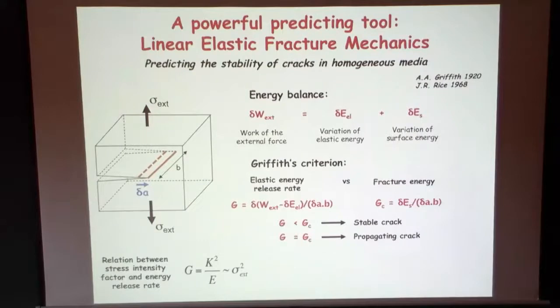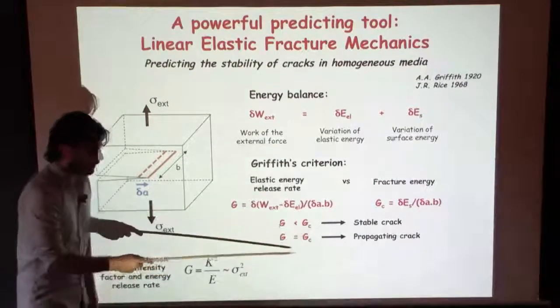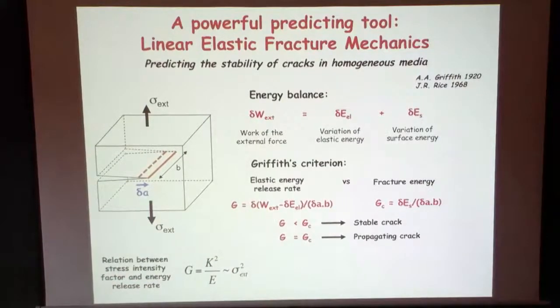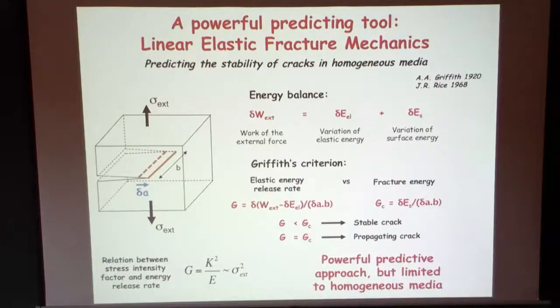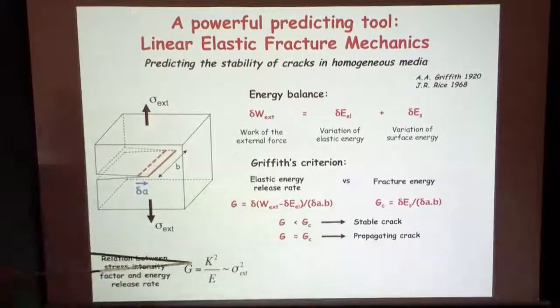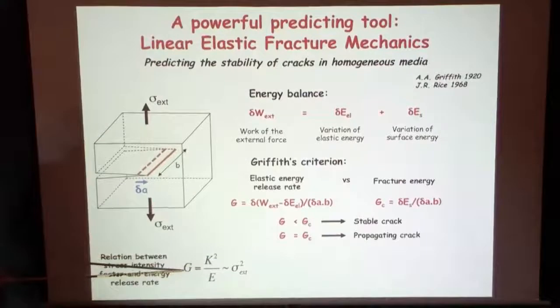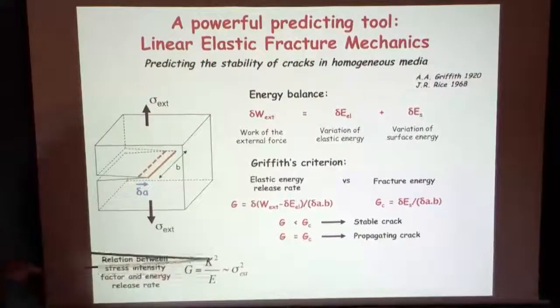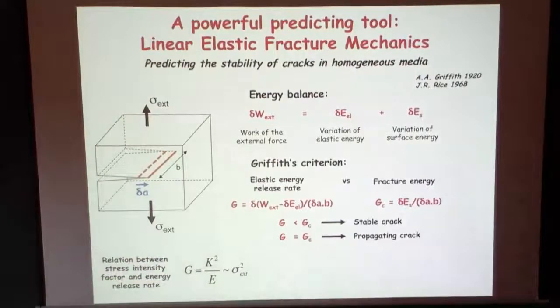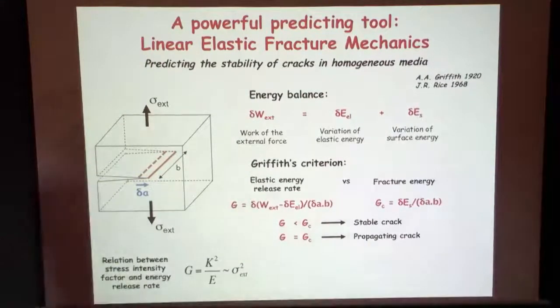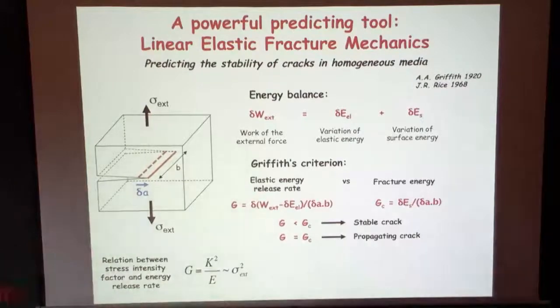And so it should be greater than or equal to GC, right? In the second condition, okay, if you provide more energy than the fracture energy, then like Jay talked about, you can use this energy as kinetic energy, or the crack grows faster, and the system will dissipate the additional energy another way. So to make a link with the previous slides and the singularity, the driving force we derived here, you can show that it's provided by this formula. It scales as K squared, where K is the stress intensity factor. You remember in the previous slide, the stress field at the tip is singular. There is a constant characterizing this singularity. And the larger this constant, the larger the driving force for the crack, and you have this relationship.